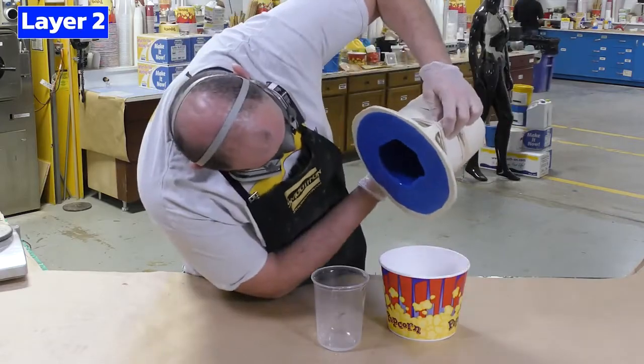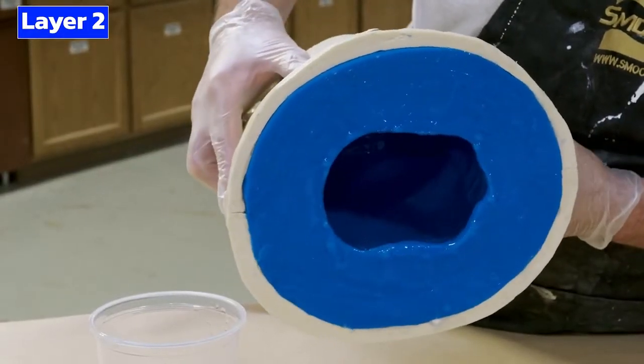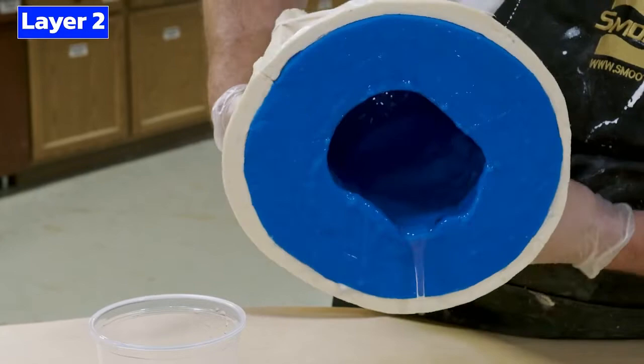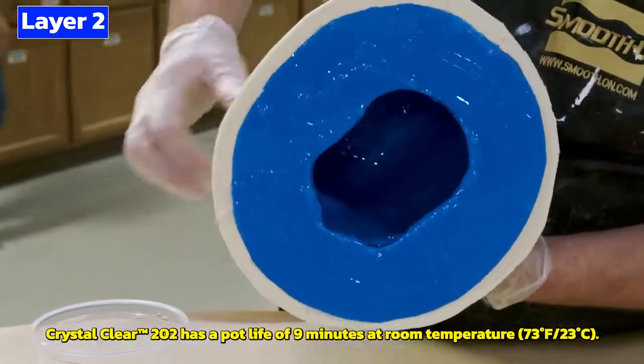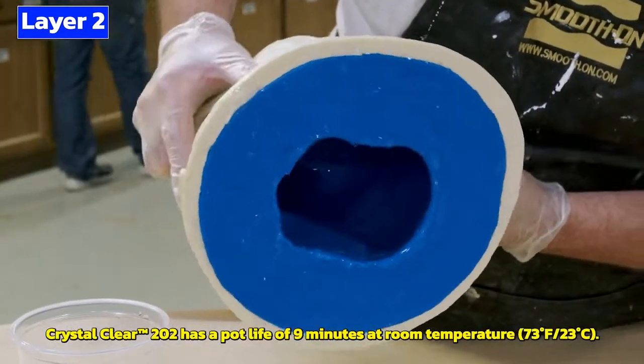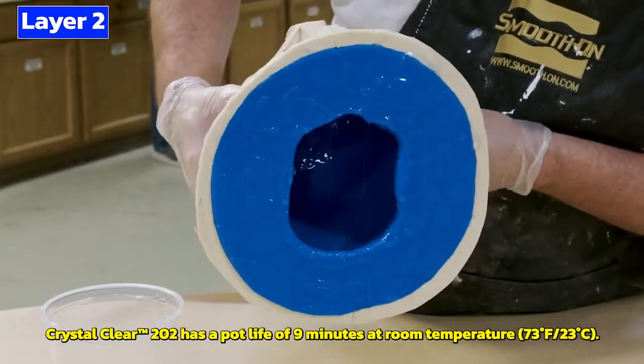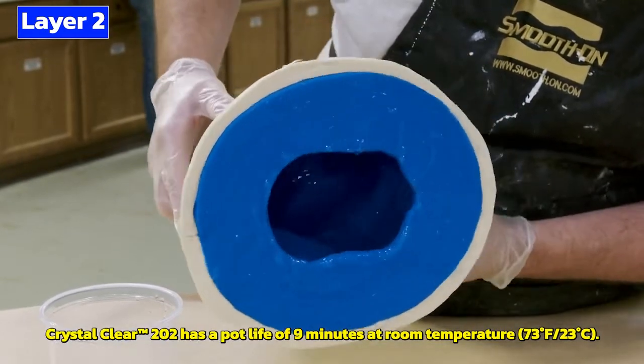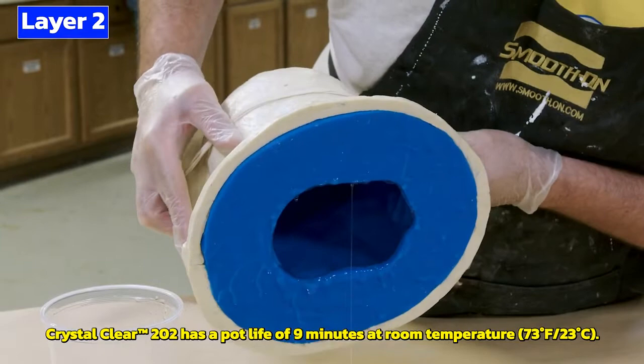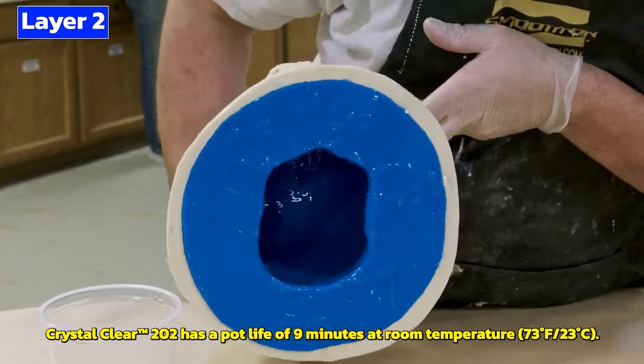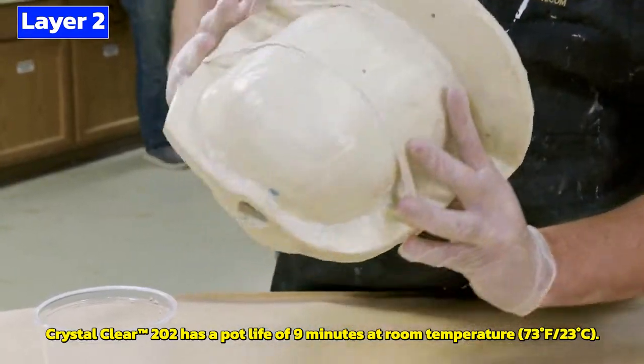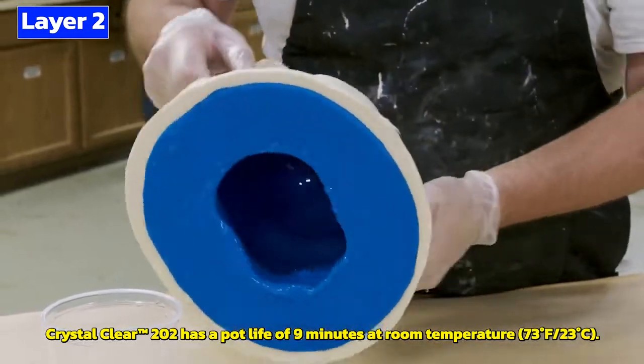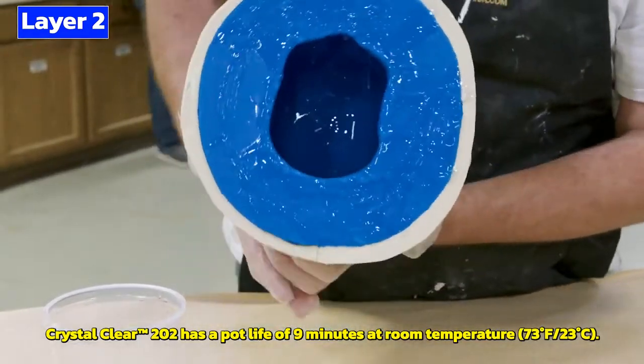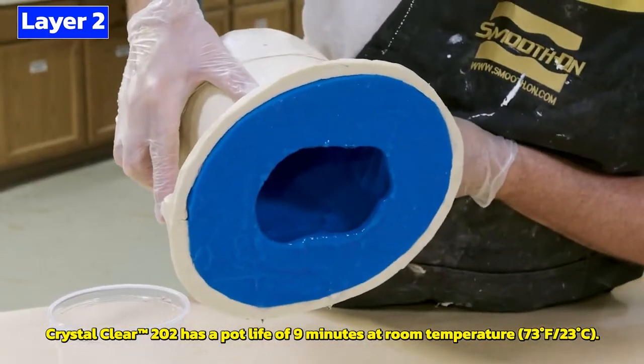Now, if you have made a hollow or rotational casting before, you probably noticed that the area around the opening of the mold or the bottom of your casting tends to be a little thinner. And that's why I'm focusing on this area and bringing material to the edge and spilling it over to make sure that material buildup there is even in thickness as throughout the casting itself.